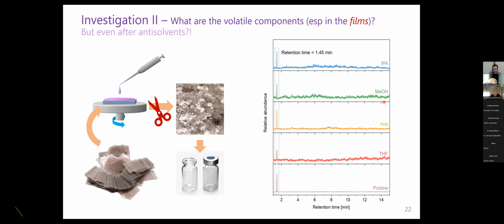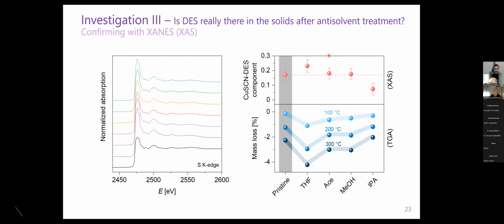When we treated the film with any of these four anti-solvents, we still found the same thing, and they were all identified as diethyl sulfide. We also did synchrotron-based X-ray absorption spectroscopy, and found the same thing, more evidence of diethyl sulfide. For some of them, especially THF and acetone, THF in particular, we observe more mass loss on the TGA, meaning there's more diethyl sulfide. And when we analyzed the X-ray absorption experiment, we also found more of the DES component in the material.